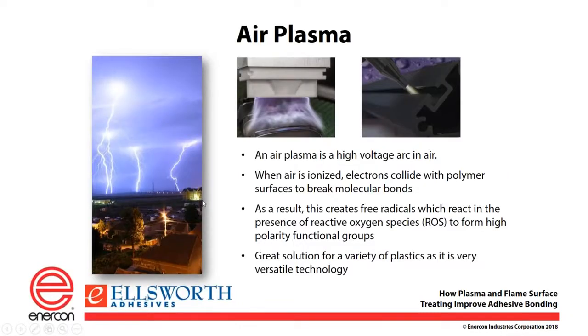Types of plasma treaters. We have three. Air plasma. This is using compressed air and a high voltage arc. So the cost of operating a single jet in this application is somewhere around 10 to 20 cents per hour. So that's what I mentioned, that's a low consumable cost. That's a couple of dollars a day. You can operate these methods. Basically, you're running compressed air past a high voltage arc. There's a little more to it than that, but that is creating the ionized gas that's going to react with your surface, give you the bonding sites that you need, cleaning the surface, and then functionalizing the surface.